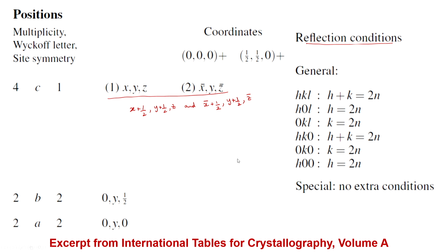So, I will have now 4 terms in the structure factor. Of course, if I put n by 4 atoms in this case, I will get a total of n atoms, and each of those could be different. But we do not need to really write the summation, because we just have to add one atom at a general position. So, I will get 4 atoms. So, just write 4 terms of the structure factor, that is good enough to analyze the reflection conditions. So, starting with x, y, z, second one I get minus x, y, minus z.